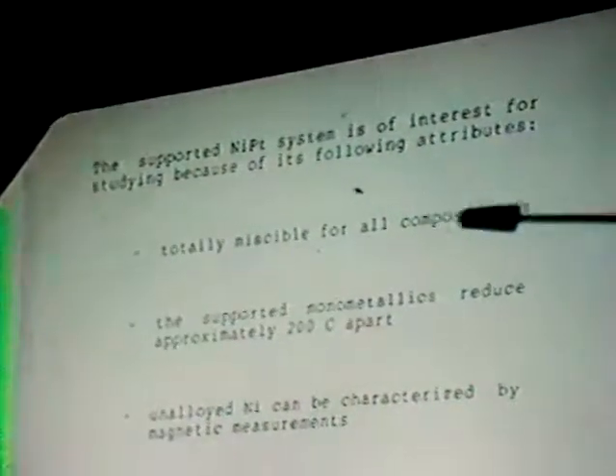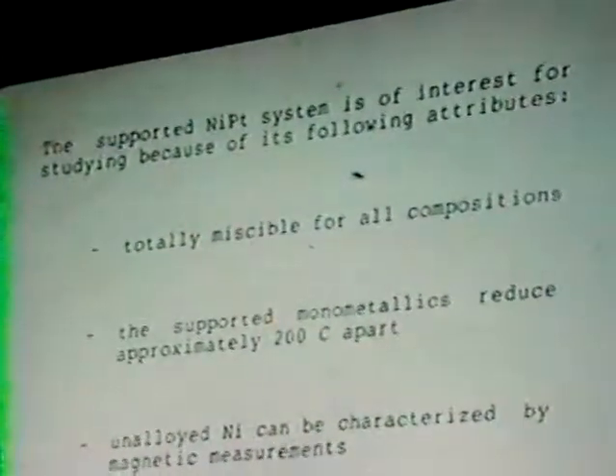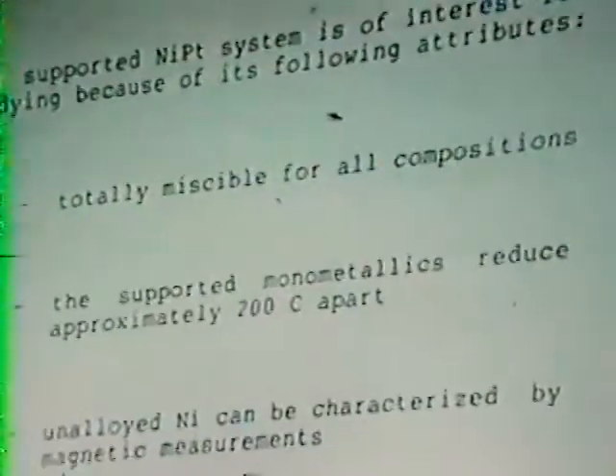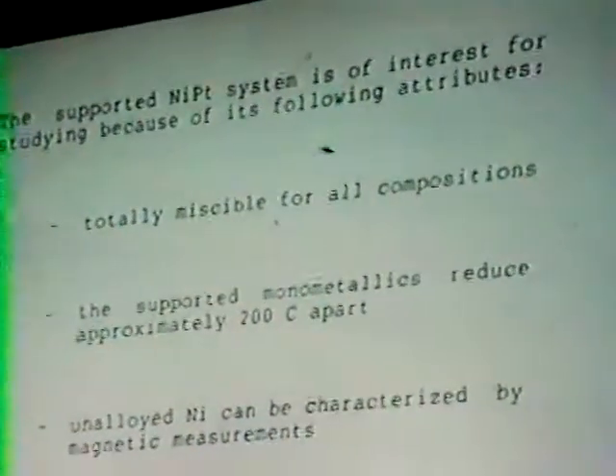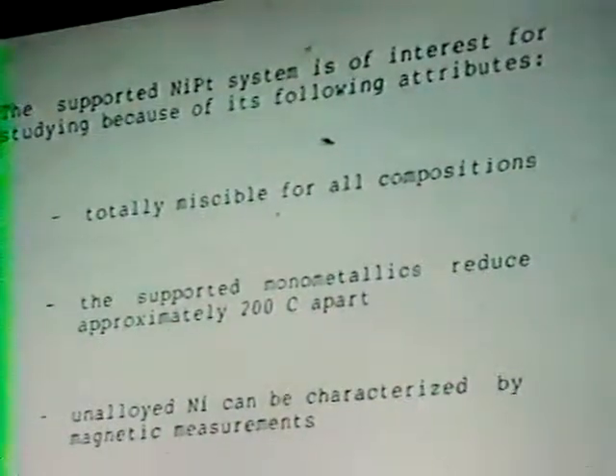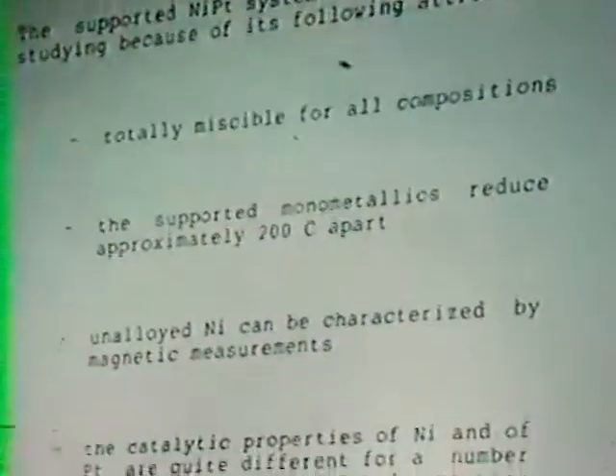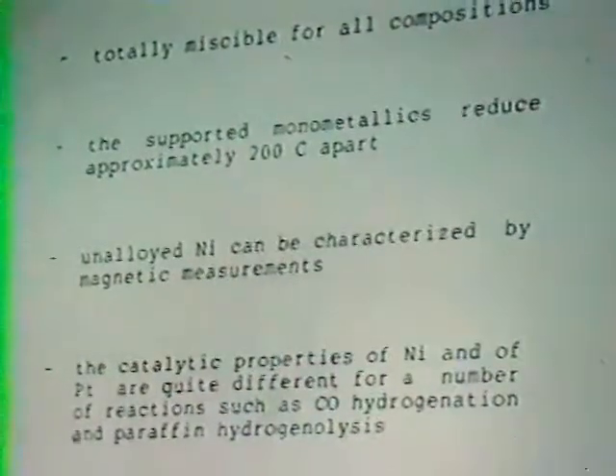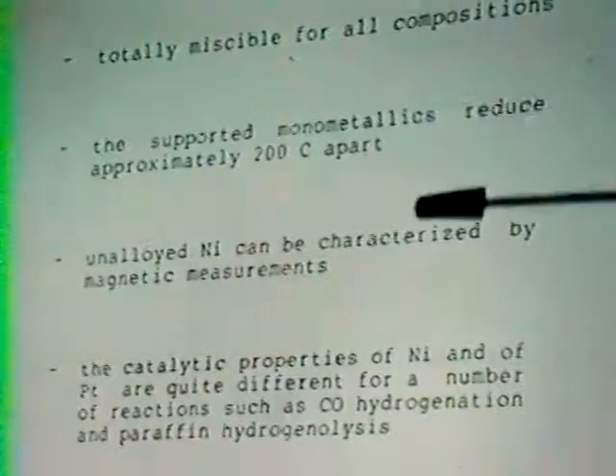The nickel-platinum system is of interest for a number of reasons, which make it sort of a model. One is that nickel and platinum are totally miscible for all compositions. The second thing is that their precursors reduce something on the order of 200 degrees centigrade apart, and therefore have significant differences in ease of reducibility.